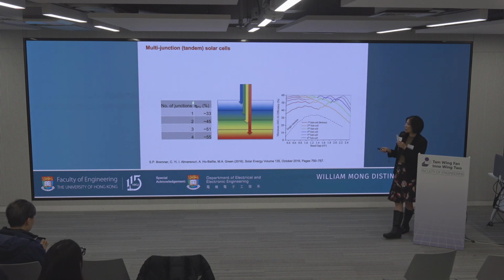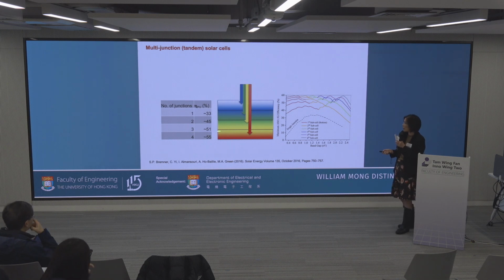Coming back to multi-junctions, as you increase the number of junctions, you are putting in material with a higher band gap. What it means is it converts all or most of the photon energy into electrical energy, and so you get a higher voltage. You add the voltages up, the current is the same, and you get 45% efficiency for two junctions, 51% for triple junction, and so on. As you can see, as you increase the number of junctions, you don't necessarily get a linear increase in efficiency. So people are stopping maybe at triple junction and quadruple junction, for 3-5 materials.